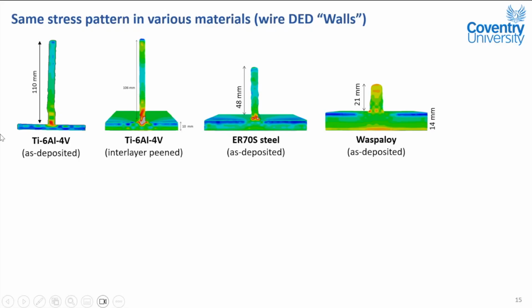We always have residual stress. The horizontal material is a substrate made by wrought material or forging. Then the verticals are walls. So these 110 millimeters are 140 layers or more. So we studied Ti-64 and also Ti-64 with interlayer hammer peening, and also a low alloy steel, ER70S steel. And this is very weldable, and also the offshore energy people like it to repair or to clad their corrosion damage, for example.